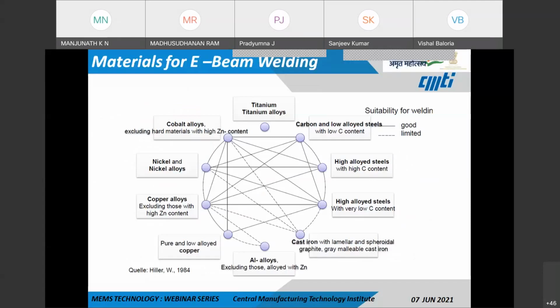And coming to the materials which are being used for e-beam welding, this graph clearly gives an idea on what materials are being used: nickel and its alloys, copper and its alloys, titanium, carbon steel, high alloyed steel, and aluminum. These are some of the materials which can be welded along with their alloys, and dissimilar metal welding can also be thought of using this graph, wherein we can have a weld between nickel and carbon steel, but nickel and cast iron is slightly challenging. So the dotted lines indicate that the welding is slightly challenging, but the straight line, the good line, indicates a better weld quality. So likewise, we can always have a ready comparison of the materials which can be welded.